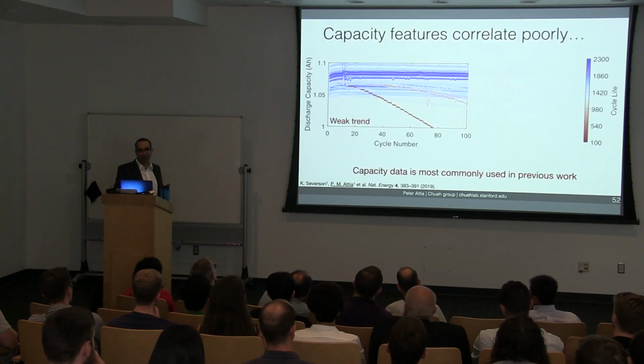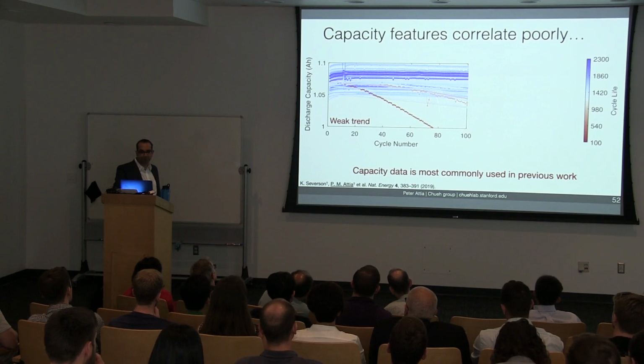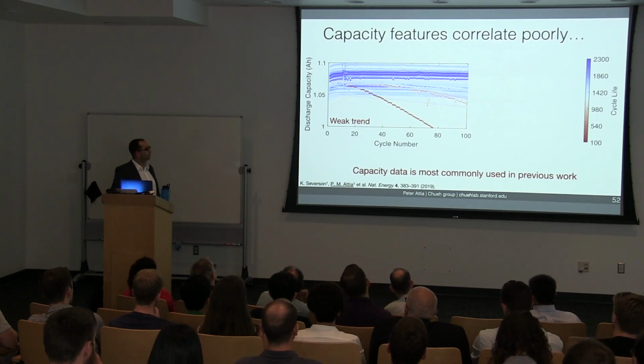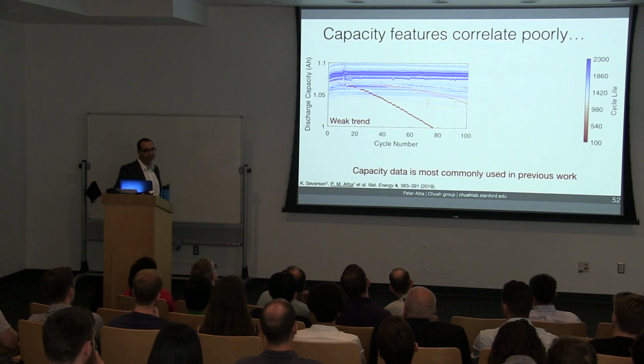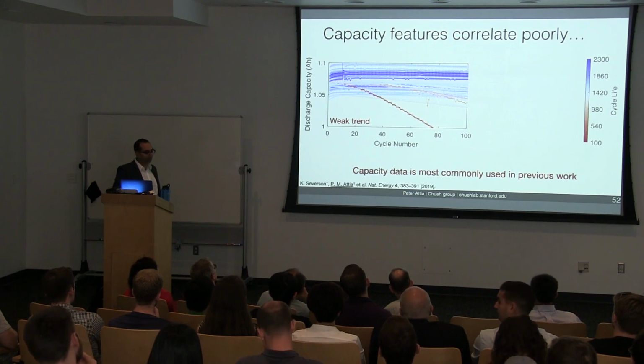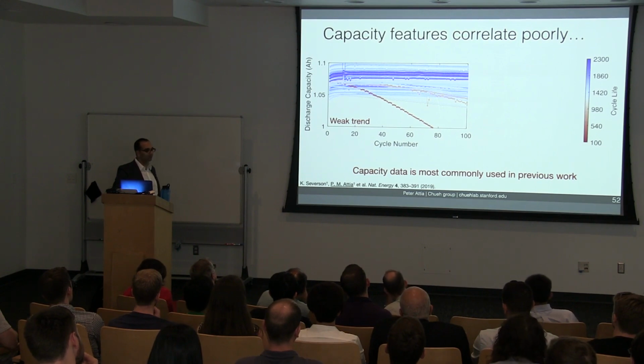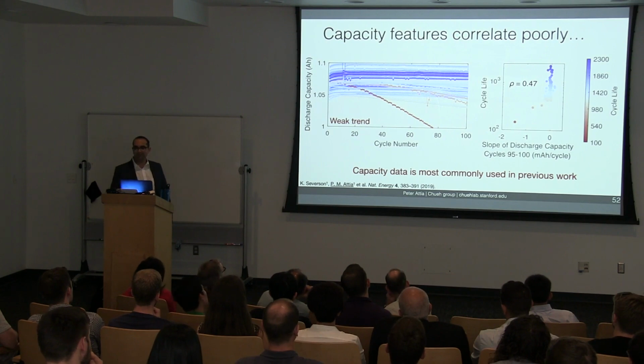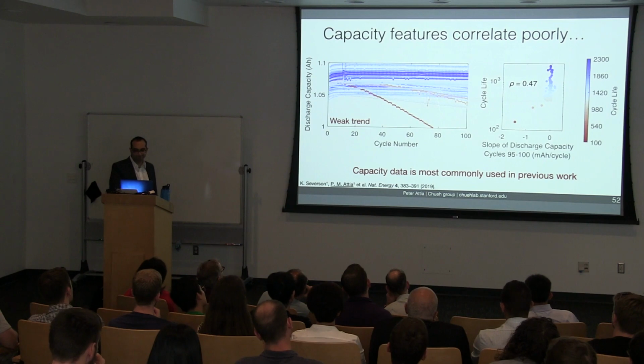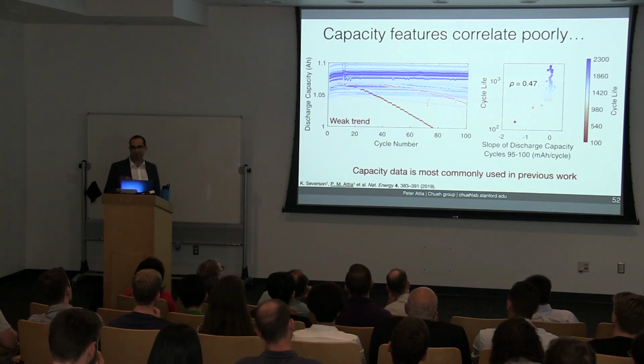Now, an important step in the machine learning approach is to generate features that we can use to build a model. So your features are just some transformation of the raw data. We started with features based on capacity. And a lot of previous work is based on capacity because it's so easy to use. This plot shows the discharge capacity for the first 100 cycles. We don't see a strong trend with color, which implies a weak relationship with cycle life. In fact, even our best capacity-based feature has a pretty weak relationship with cycle life. The correlation coefficient of this feature is just 0.47.